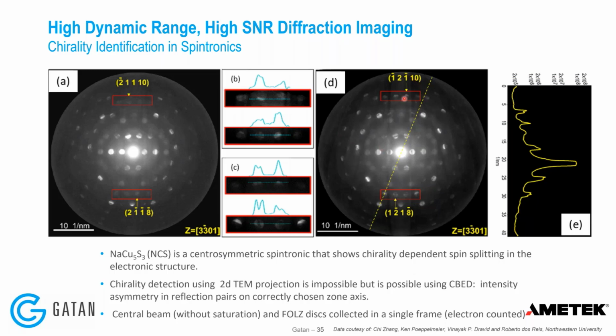As you can see here, for example, on the right-hand side, if you look at these two boxes, we have zoomed into those, and if you draw a profile line, you can see the diffraction intensity in these pairs of reflections in the first order Laue zone is inverted. And this is showing you the chirality in the sample if the sample is in the right zone axis. And to show the dynamic range, I have again drawn a profile line along this dashed yellow line, which is shown here on the right hand side. Again, you can see the intensities in the reflections and diffraction spots, and also the central beam shown in the middle.